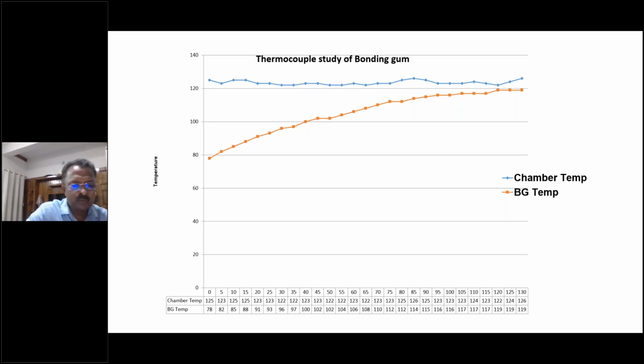Second, the chamber temperature is set at 125 degrees. And the bonding temperature: initially the bonding is cool inside the tire. So the temperature has to reach the bonding layer. It has to cover the tread rubber section to the bonding point. So initially the temperature is very low, and gradually it picks up. And from this data, we can work out the equivalent cure. For bonding gum, an equivalent cure of 25 minutes is maximum. It's enough.